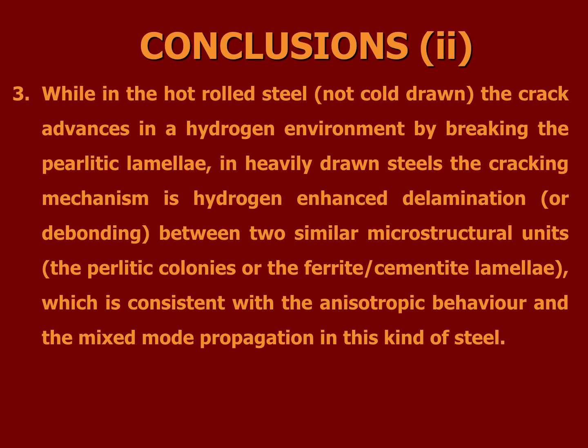In heavily drawn steel it could be HEDE, hydrogen-enhanced decohesion or delamination, while in slightly drawn steels or hot-rolled steels it is tearing topography surface, closer to the mechanism of HELP, hydrogen-enhanced localized plasticity, a kind of localized tearing, localized plasticity enhanced by hydrogen. Then we have HELP for slightly drawn steels, hydrogen-enhanced localized plasticity by tearing topographic surface, and HEDE, hydrogen-enhanced decohesion, delamination in the most heavily drawn steels, in which the decohesion or delamination is produced in the lamellar ferrite-cementite lamella, or in the bonding of the colonies.